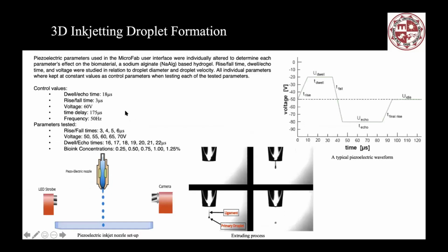And these are the inkjetting droplet formation setups we investigated on the sodium alginate-based hydrogel. Here are the control values: the echo time, dwell time, rise time, the voltage, frequency, right? And the parameters we vary are the rise and fall times, voltage, echo time, and the bio-ink concentration. For the concentration, we prepared five different concentrations for testing. And here's the piezoelectric inkjetting nozzle setup, right? Here is the LED strobe, and this is the piezoelectric nozzle. It can be activated or triggered, and then it will release one drop at a time.